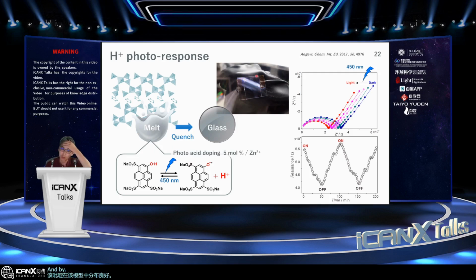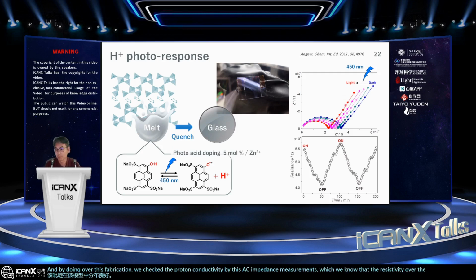And after this fabrication, we checked the proton conductivity by AC impedance measurements, which gives the resistivity of the ion conductivity.